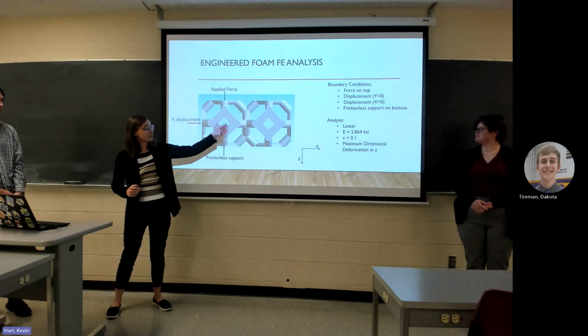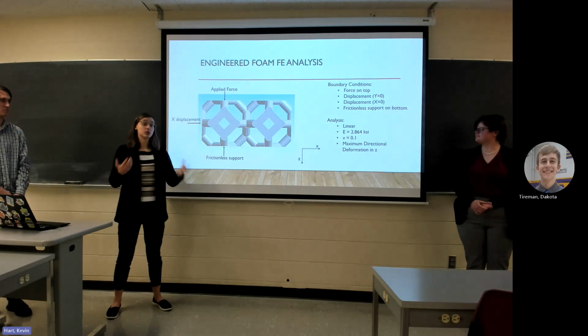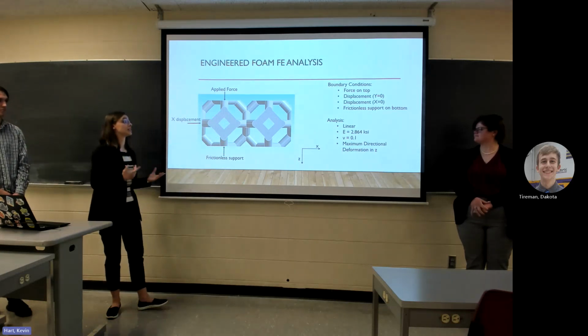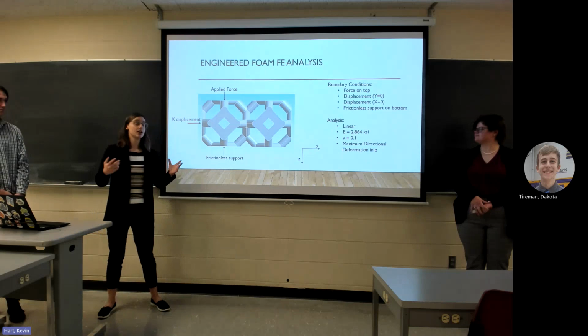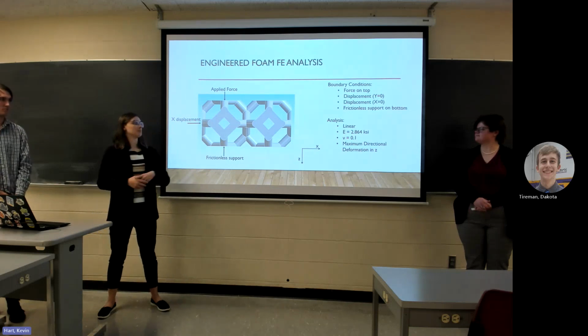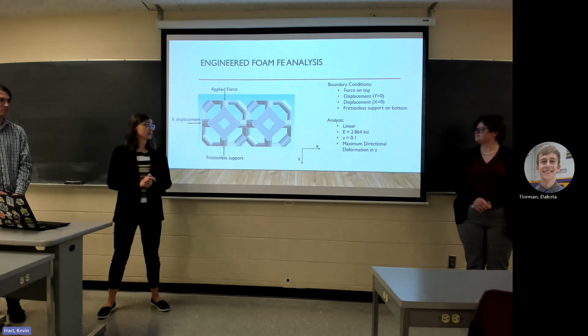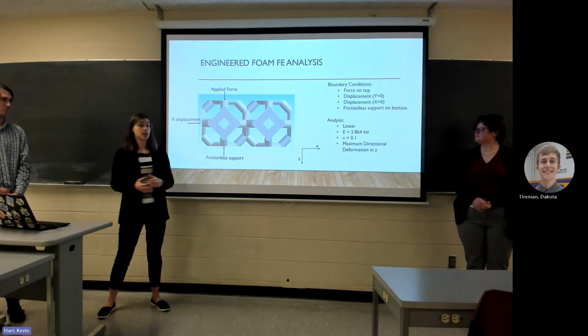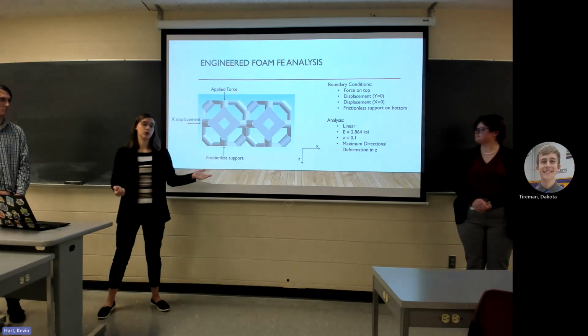So after we figured that out, the compression test that we did gave us our material properties. So it gave us an average Young's modulus of 2.86 KSI, and then due to the behavior of foam, we use a Poisson's ratio of 0.1.